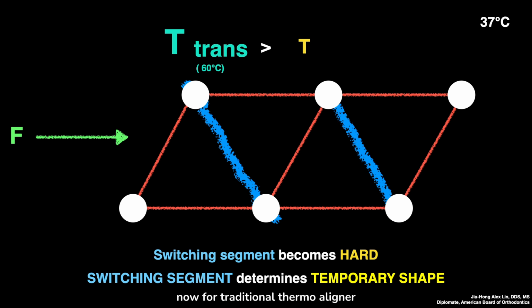Now for a traditional thermal aligner, you're done, right? There's no way you can regain the elasticity, and that's probably one of the reasons that we see off track. So instead of blaming patient compliance or bad staging, a lot of the off track that we're seeing is probably because of the material losing strength before the teeth are moved to their planned position. But this may not be the case for polymers with shape memory effect.